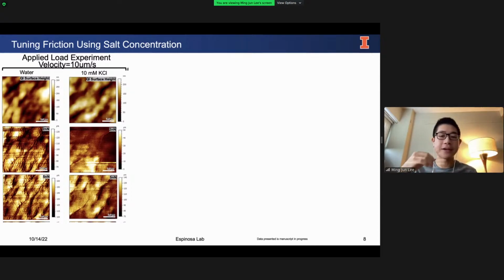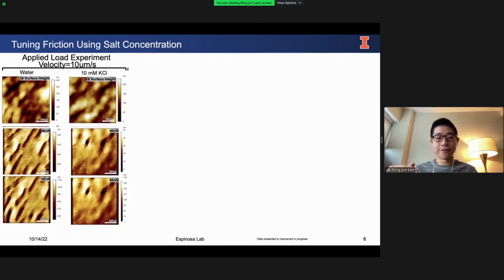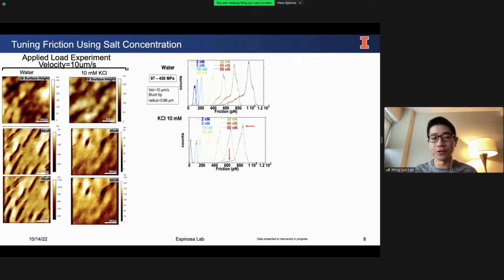And then I apply different forces, different applied loads onto the hydrogel, starting as small as 2 nanonewtons that you see in the middle row, followed by 5 nanonewtons, and then there are some intermediate values, and finally ending in 40 nanonewtons and 50 nanonewtons. For your convenience, I have summarized the friction force values into histograms here. So we have the water condition on the first column, corresponding to the first row of histograms, and then the salt solution condition, which is the second column of AFM images, corresponding to the second row of histograms.